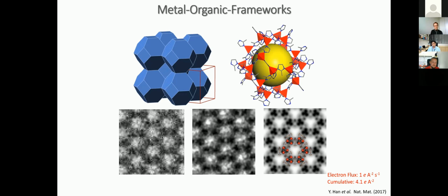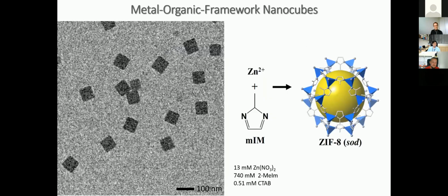Now we're talking about 1 electron, 4 electrons. Earlier I was showing you movies that are like 100 seconds long, and we were putting thousands of electrons to drive the processes. Well, we can't do it here. Your material is just going to evaporate or disappear, right? So this is the structure of the ZIF. To really understand the nucleation of the ZIF, we can't image it at very high resolution, so we cannot identify whether it's a crystal or not. Because if you try to image with very high resolution, you have to pump in a lot of electrons, and then you have to image the entire process. It takes time, and you're going to destroy your specimen, right?